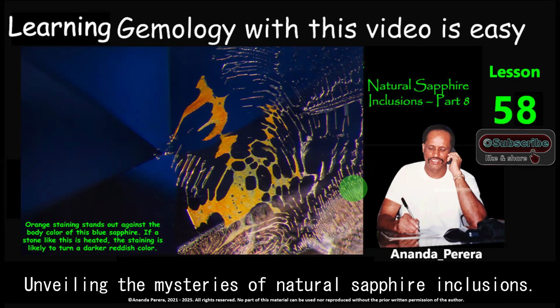natural sapphire inclusions. Here in this cover photo, you can see this is the natural color of the stone and the orange color stain. The orange color stain stands out against the body color of this blue sapphire. If a stone like this is heated, the staining color turns to a darker reddish color. We are learning that in the next part, that means a heated inclusion part. We are studying the natural inclusions here. So we are moving to the next slide.